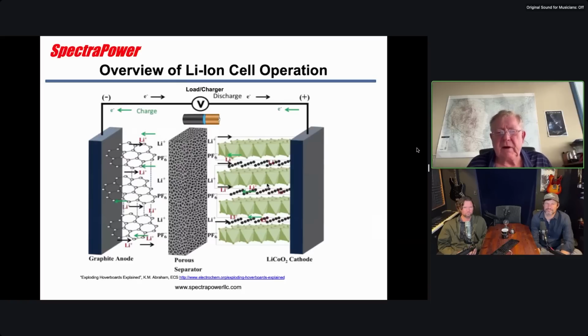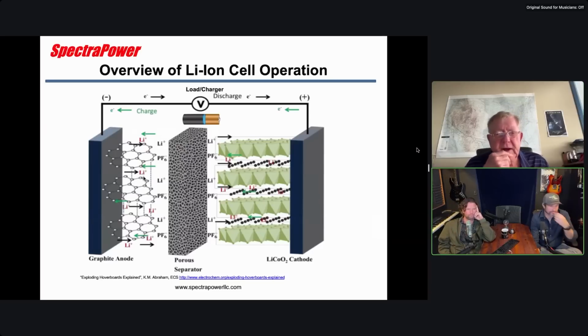That's the charging process. So what's going to happen is the electrons are going to get stripped by the charger and pulled over into the anode, which makes that a more negative charge. And so the lithium gives up its extra electron in the outer shell and moves over into the graphite, where the process is called intercalation. And what happens is it goes into these graphite rings, if you will. It's stable there because that electron that it gave up on the other side, it picks up over here and is in a stable chemical configuration in the graphite.